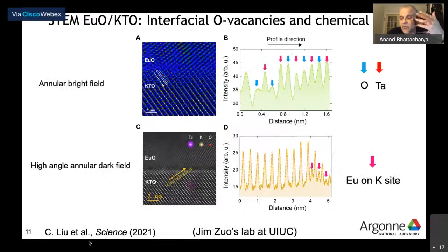We found when we looked closely with TEM at our samples, using both annular bright field, which is sensitive to oxygen and light atoms, and high angle annular dark field imaging, which is sensitive to heavy atoms, that the interface is not what you would draw in a PowerPoint picture. What's really going on is that near the interface between EuO and KTO, in the KTO, there are actually some oxygen vacancies. You can see this in the annular bright field image. If you look on your left, the top left is the direction of the arrow going into KTO. On the right panel, B, if you start from the left, that's where the interface is. As you go into the KTO, you find that the intensity of the blue, in the places where those blue arrows are, that stands for where the oxygen ought to be, there's a suppression of that intensity near the interface.